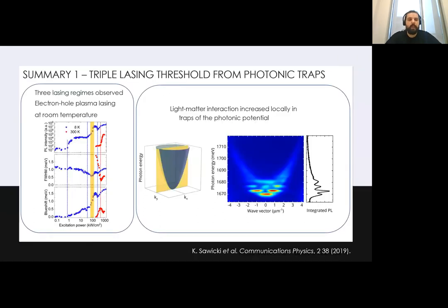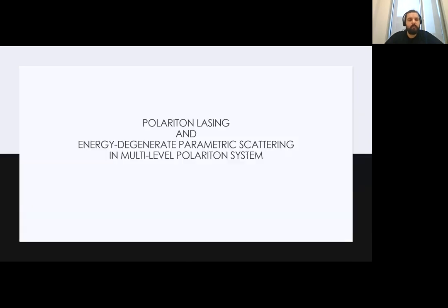of 3.5 micrometers. So it brings me to the summary of the first part of my talk, where I showed a qualitatively new cadmium selenide and telluride microcavity, which allows us to observe three lasing thresholds in the emission at room temperature. I showed that photonic traps in the microcavity are involved in the emission. So let's move to the next part, in which I switch the topic a bit, and I